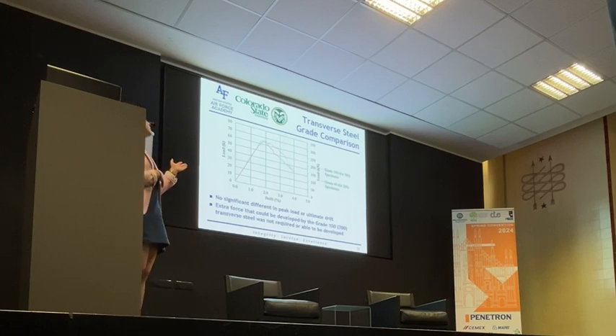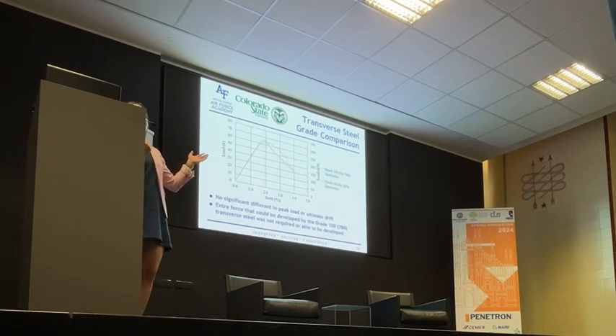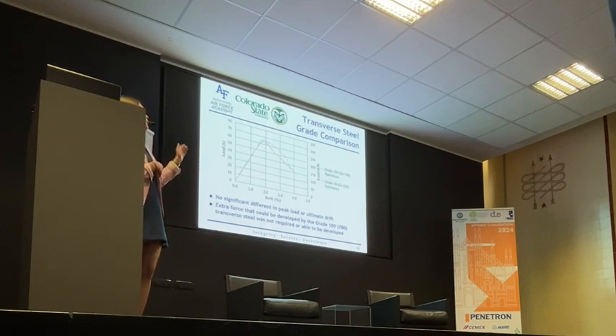This is our transverse steel grade comparison. We varied between grade 100 and grade 40. We had 3 grade 100 and 4 grade 40 specimens, and all of the grade 100s failed in some sort of shear capacity. Also, not a huge difference in the peak load or drift.